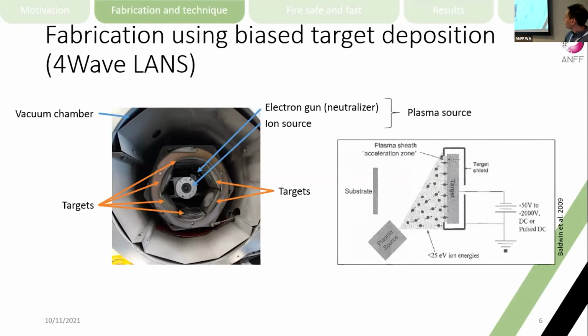4-wave, I show there the inside of 4-wave, is basically a vacuum chamber. It contains 6 material targets, and on the far end is basically an electron gun and an ion source, which together build a plasma source. And you can imagine the substrate would be on our end, built into the lid, which is currently open. And the whole assembly is basically a hexagon-shaped prism with the plasma source on one end and the substrate on the other end. On the right-hand side, I show you how bias target deposition works.